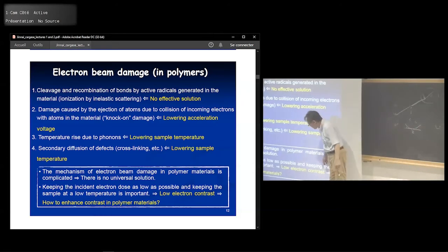The thing we need to think about is, then how do we lower the beam damage? The only thing we can essentially do is lower the dose. We try to get the image with the lowest amount of electrons on the sample. Typically, when you do this, the electron contrast becomes worse. If you put lots of electrons, of course the sample will be damaged. But if you take just one picture and don't care about it, and you put lots of electrons, then even though the contrast of the sample is small, you have a better image. But thinking about beam damage, you need to lower the dose. Then the contrast gets worse.